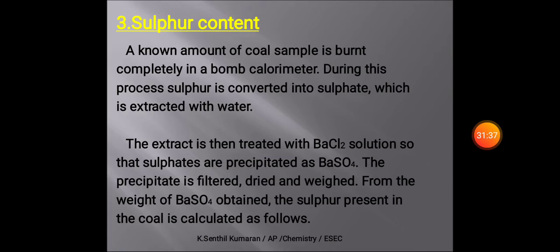Same thing as the percentage of carbon and percentage of hydrogen. Percentage of sulfur equals the weight of the barium sulfate divided by the initial weight of the coal sample, into the atomic weight of sulfur, that is 32, divided by the molecular weight of barium sulfate, that is 233, into 100. 32 is the atomic weight of sulfur and 233 is the molecular weight of barium sulfate. So using this formula we find the percentage of sulfur content.